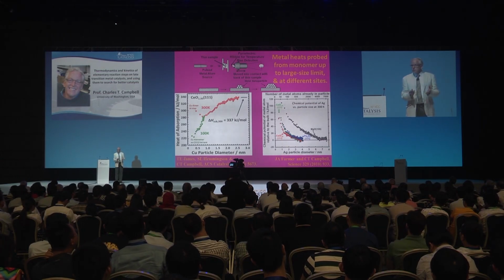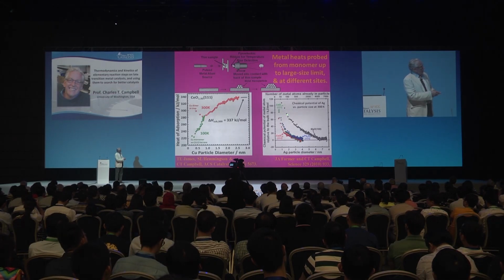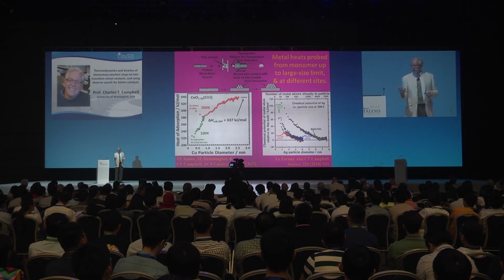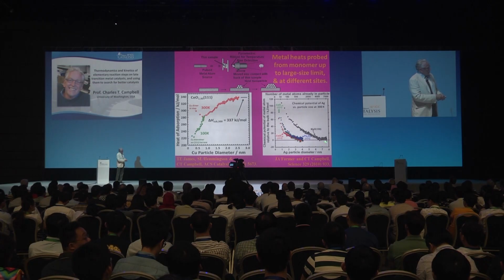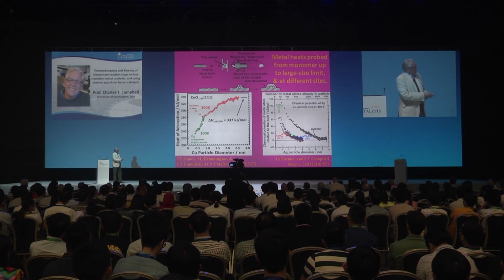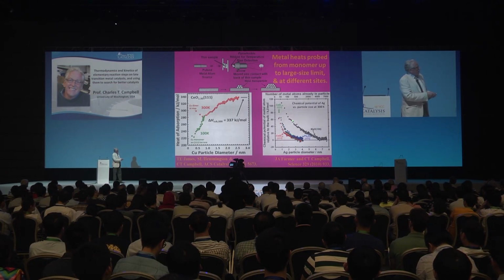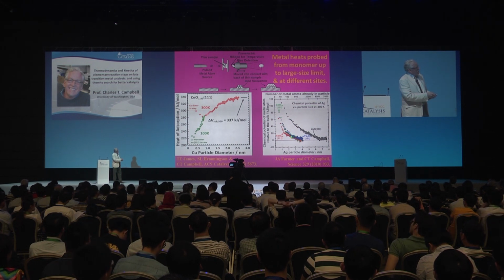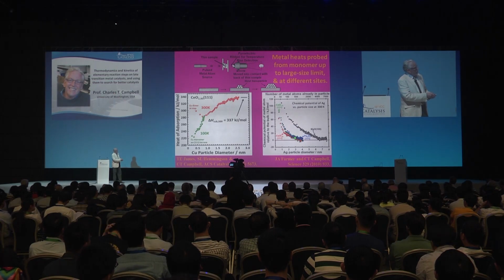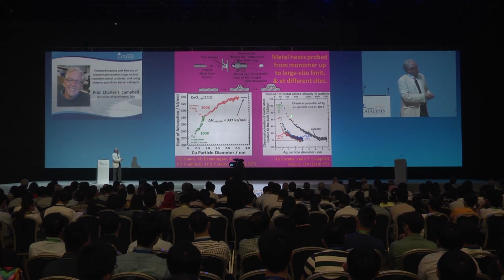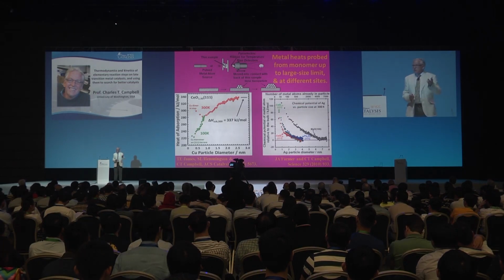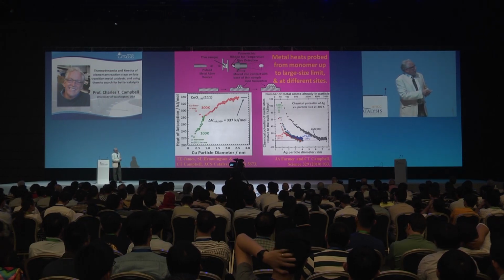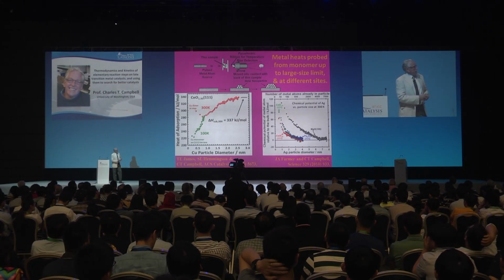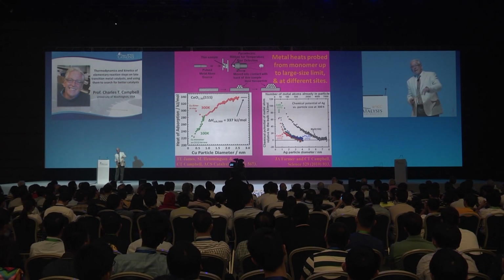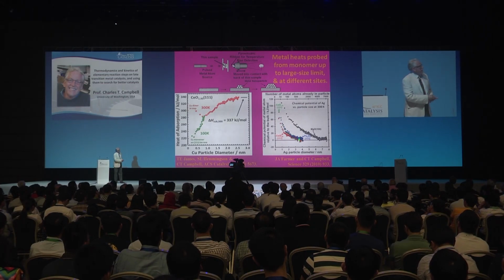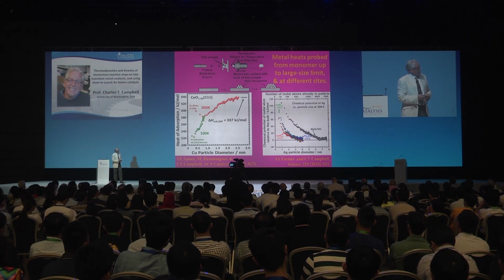This is why it's hard to keep metal atoms in small clusters, because they're less stable by, for example, on MgO, they're less stable by 80 kilojoules per mole of metal atoms than a large particle of MgO that's bigger than 6 nanometers. The other thing you can see from this is that the metal atoms on MgO are much less stable for the same particle size than if they're supported on a slightly reduced ceria, and more reduced ceria is even more stable. And this difference really has to do with that other bond. Okay, this decrease has to do with the fact you're getting fewer metal-metal bonds as you go to smaller particles. But the difference for the same particle size here is associated with the fact that there's also bonds of the metal cluster downward to the oxide. And the stronger that is, the further downhill you are in chemical potential.